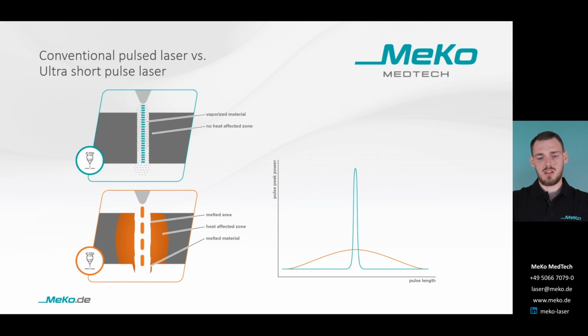As the name already says, those lasers have extremely short light pulses compared to conventional lasers. The sketch on the right side shows the shape of a single laser pulse, while the orange line represents the conventional laser, and the green line the USP laser. And here it is important to say that this is only schematic and it is not a true representation of the ratios. The very high pulse peak power combined with the very short pulse length results in a single laser pulse with an extremely high energy density.